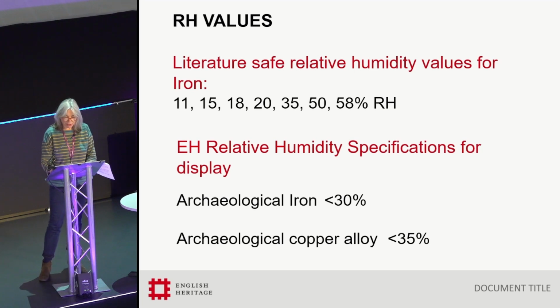We aim to achieve lower values in storage using silica gel. Stewart and lock boxes are used. Irregular or larger objects are placed within heat-sealed polythene bags and sealed with silica gel. We're gradually changing our 4-spot indicator cards, that's the 10, 20, 30 and 40 type, to the 3-spot indicators reading 5, 10 and 15 for monitoring.